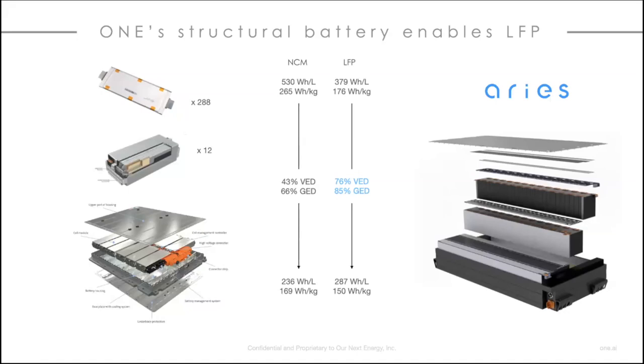In the days that I ran product development at A123, I think it was around 220 watt hours per liter. And the cell was maybe a little more optimized for power because the battery packs were very small. Today's LFP, which are being optimized exclusively for energy, in that level of energy density, 379 is a really good number. And if we can maintain 76% of that flowing to the bottom line, then we can enable a higher performing LFP pack using cell to pack as an architectural shift.